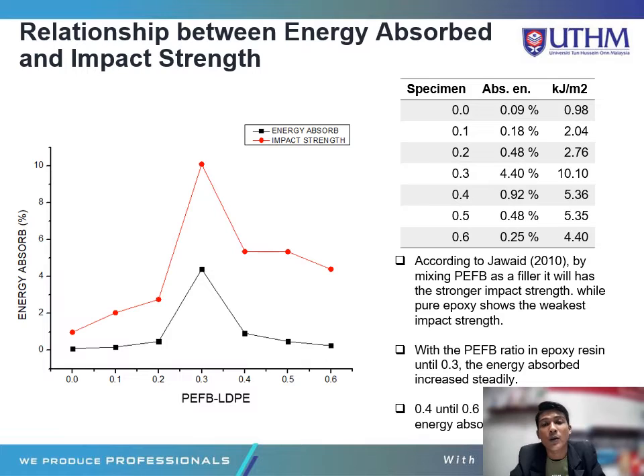For ratio 0.3, the energy absorbed increases to 4.4% and the impact strength is 10.10. For the ratio of 0.4, the energy absorbed is 0.92% while the impact strength is 5.36. For ratio 0.5, the energy absorbed is 0.48% while the impact strength is 5.35. For 0.6, the energy absorbed is 0.25% and the impact strength is 4.4.